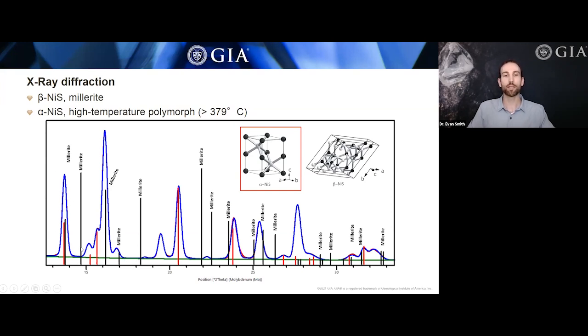Instead, we see peaks that actually match up with these red lines here. And these red lines correspond to the alpha nickel sulfide, which is a higher temperature polymorph that's never been observed in nature before. So this was sort of the aha moment that we're looking at something that hasn't been observed as a naturally occurring crystal before. And therefore, this is potentially a new mineral. It might be this nickel sulfide here. So we've got the crystal structure down pat here.